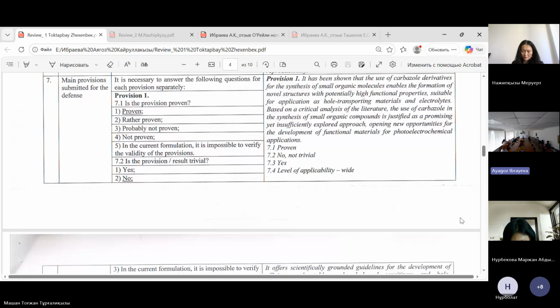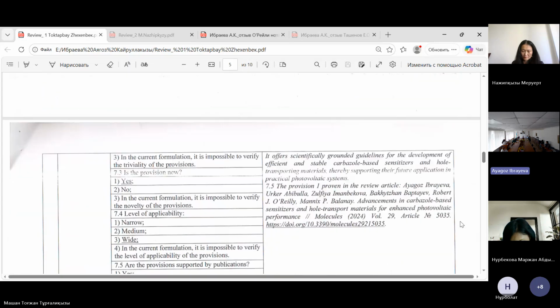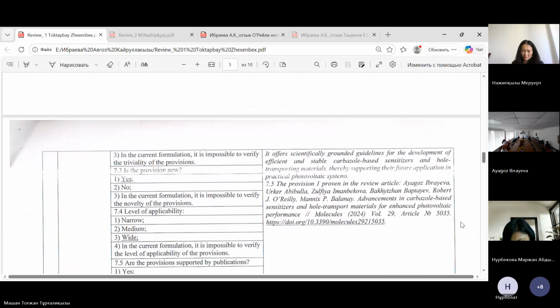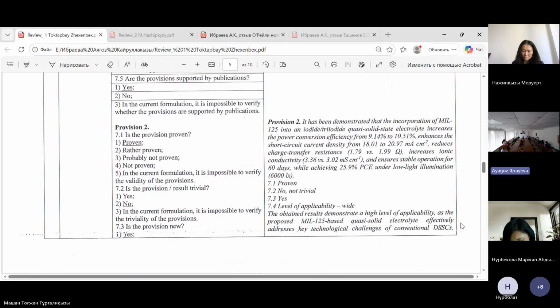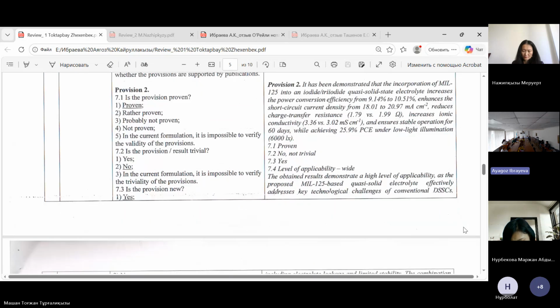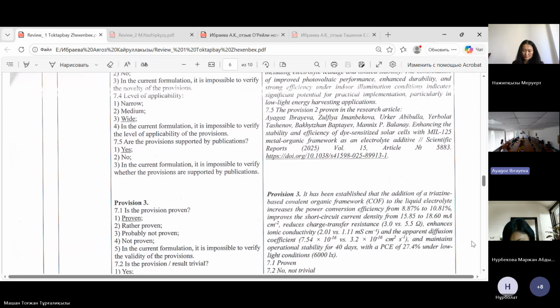And provision 2 has demonstrated that the incorporation of MIL-125 into iodide/triiodide quasi-solid-state electrolyte increases the power conversion efficiency from 9.14% to 10.51%, enhances the short circuit current density, and reduces the charge transfer resistance. Based on provision 2, one paper was also published in Scientific Reports.